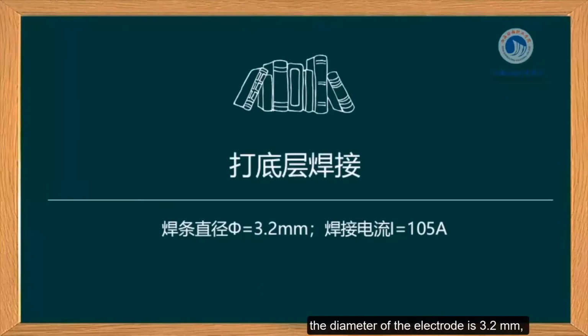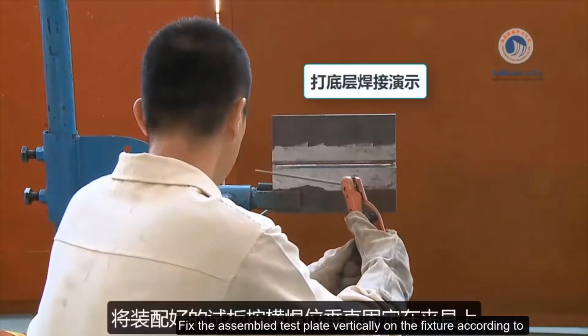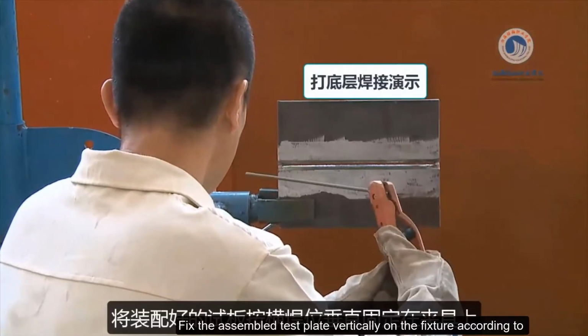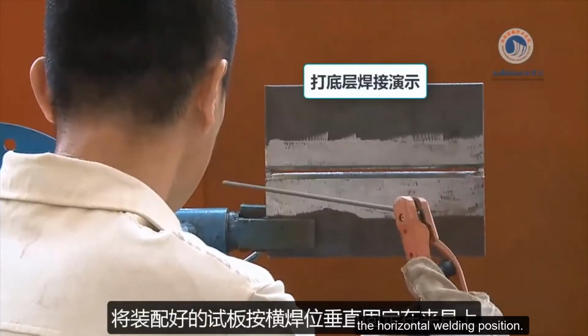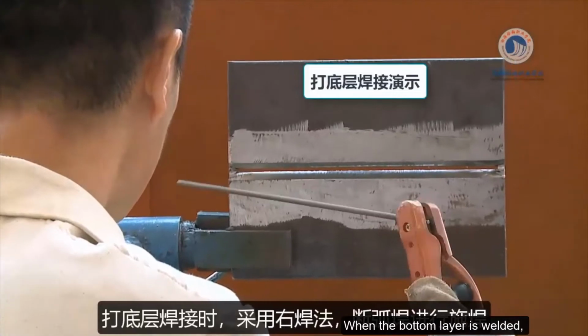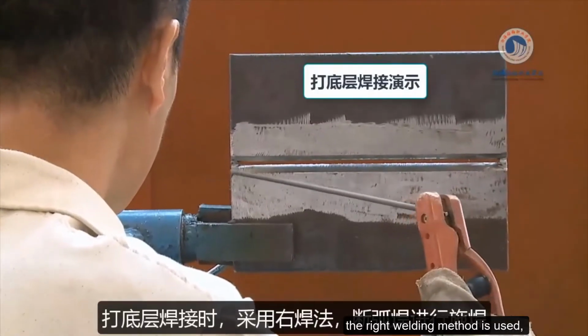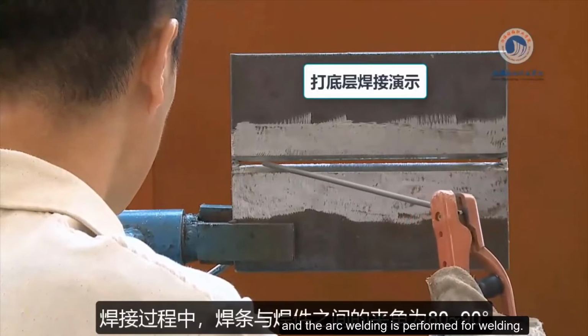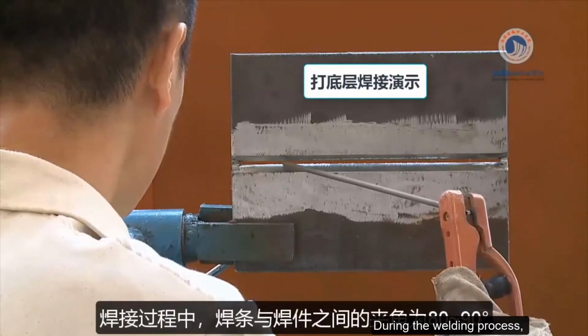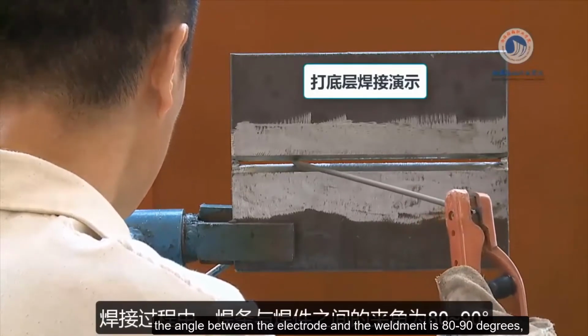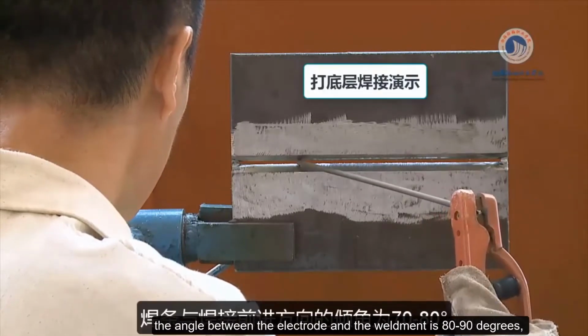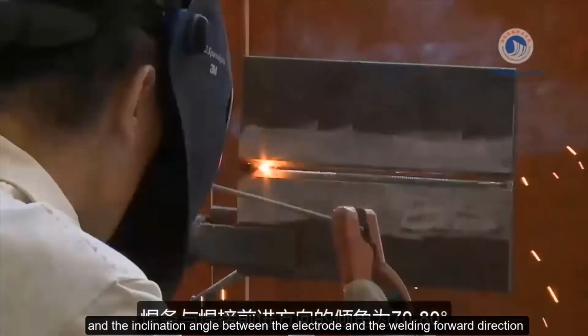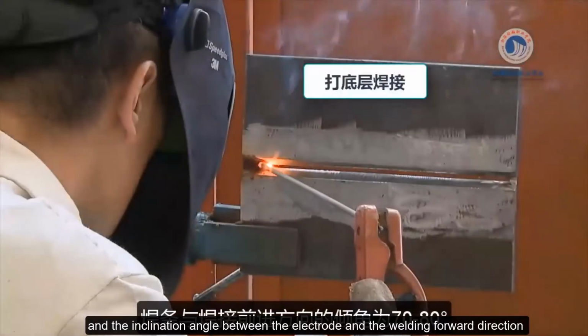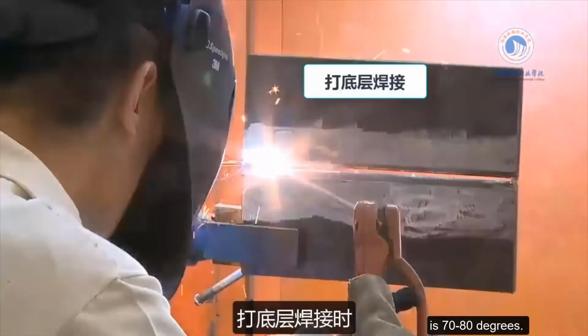The diameter of the electrode is 3.2 mm, and the welding current is 105 amps. Fix the assembled test plate vertically on the fixture according to the horizontal welding position. When the bottom layer is welded, the right welding method is used, and the arc welding is performed for welding. During the welding process, the angle between the electrode and the weldment is 80 to 90 degrees, and the inclination angle between the electrode and the welding forward direction is 70 to 80 degrees.